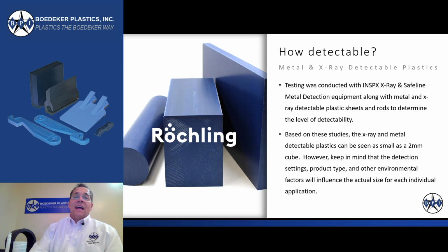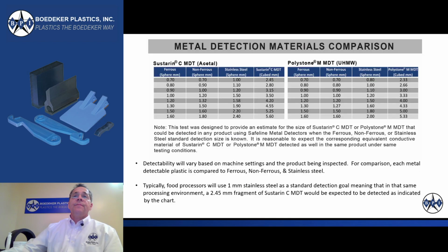materials could be seen actually down as low as about 2 millimeter cubed, which is certainly much lower than the 7 millimeter FDA requirement. But again, very important to point out that those environmental factors will play an influence and have a huge role in exactly how detectable each plastic piece will be in each manufacturing scenario. But for our test, I'll explain what we did here.